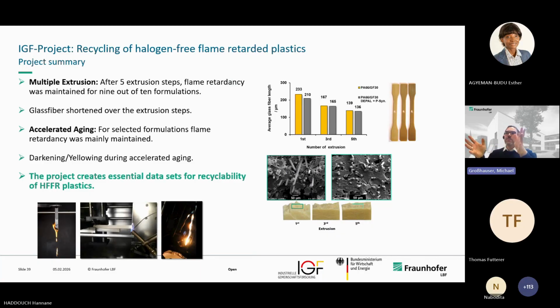So we had several results here. From multiple extrusion, after the 5 extrusion steps, flame retardancy was maintained for 9 out of 10 formulations. And the 10th one was not going that bad. It was just a small degradation, but still in a good range. And glass fiber shortening, you see it on the right side here, is happening over this time. So the problem was not the flame retardancy. The problem was more that the material and the glass fibers decompose over time.